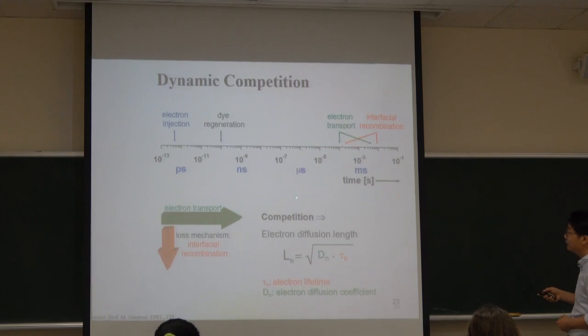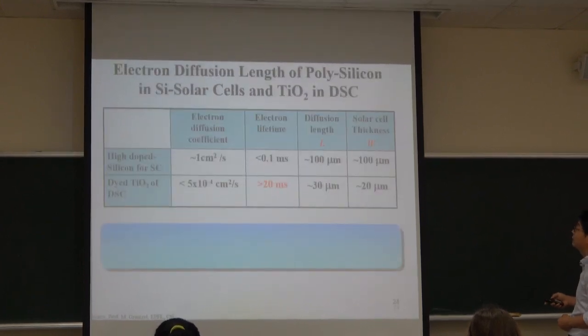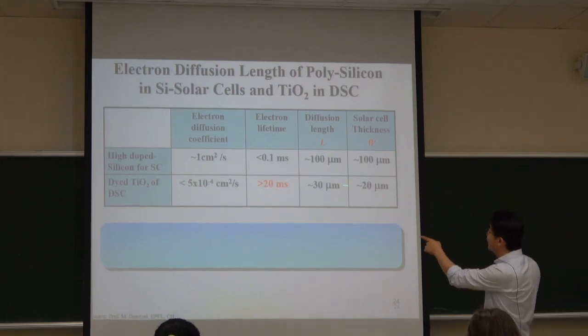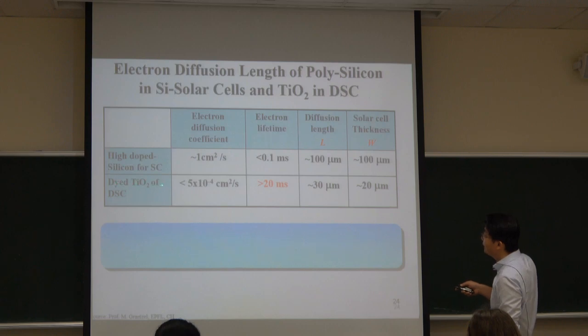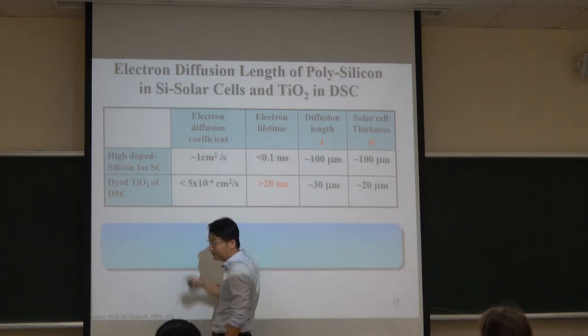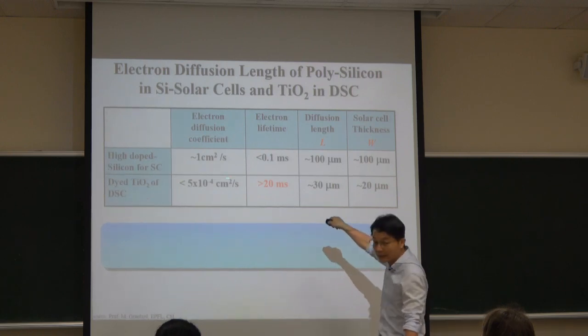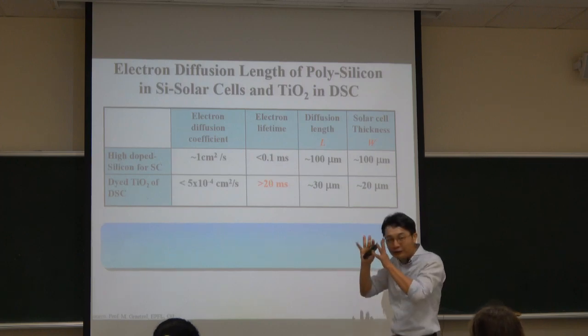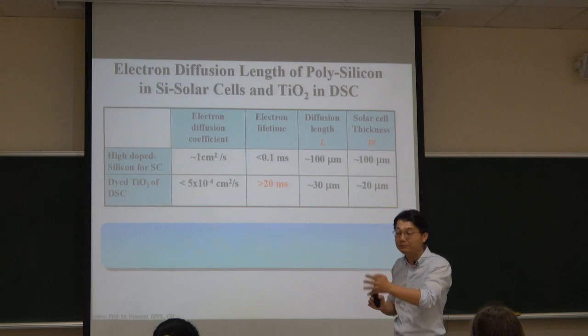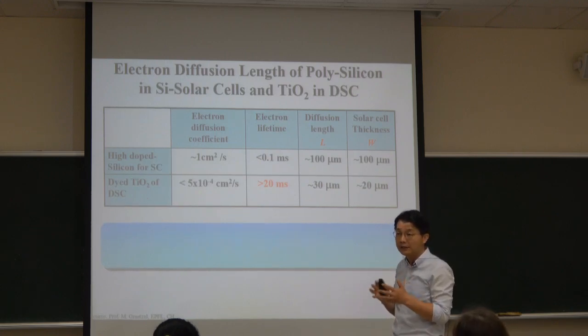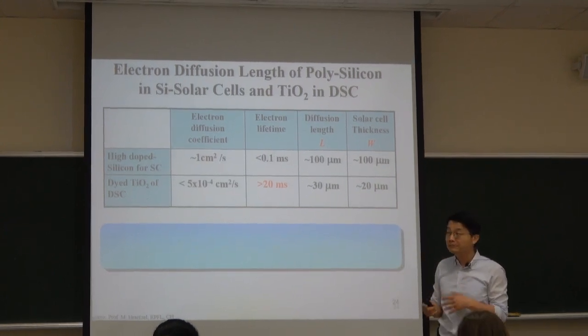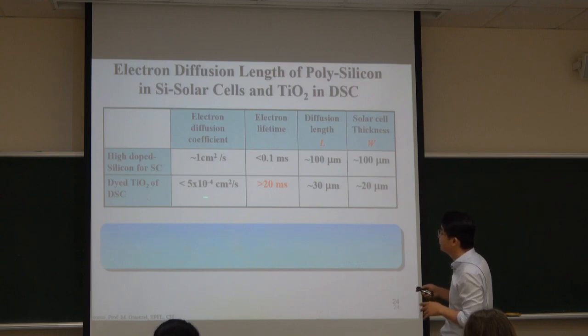We already talked about this in the competition. So this is the electron lifetime and the electron diffusion coefficient, so-called diffusivity, in the TiO2. If you look at this table, let's look at the bottom side. For TiO2 nanoparticle, the electron diffusion coefficient is about 10 to the minus 4. And for lifetime, if the material is designed very poorly, the lifetime is very poor. But if the TiO2 you design has high crystallinity, then probably you can have 20 millisecond.